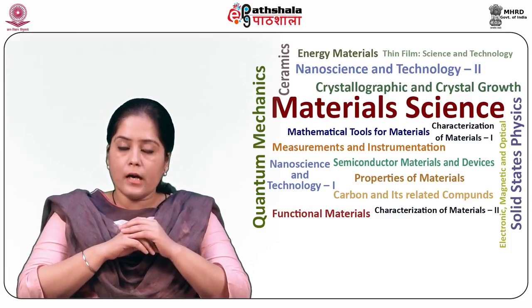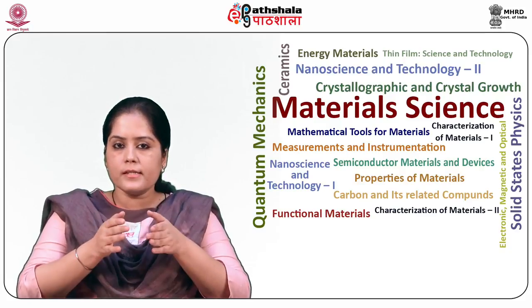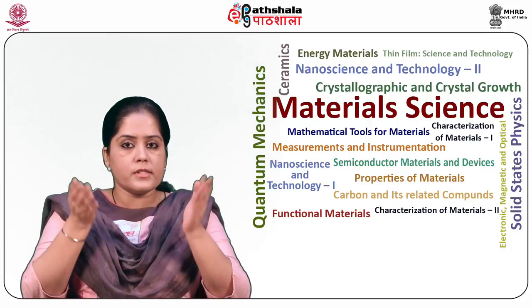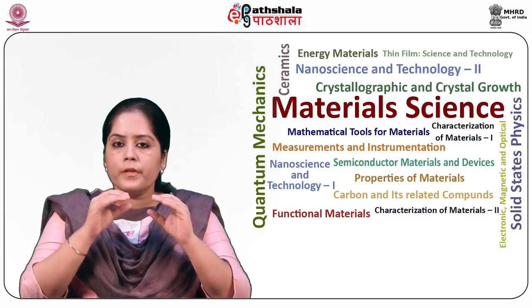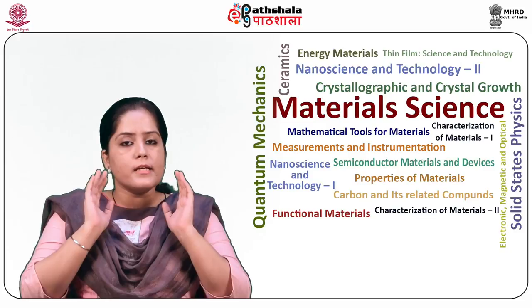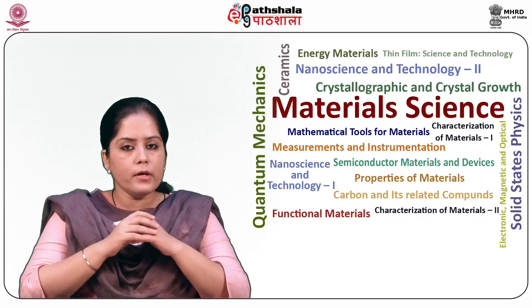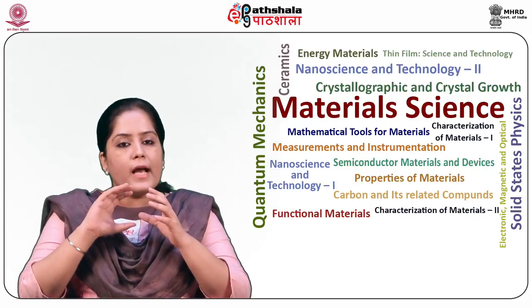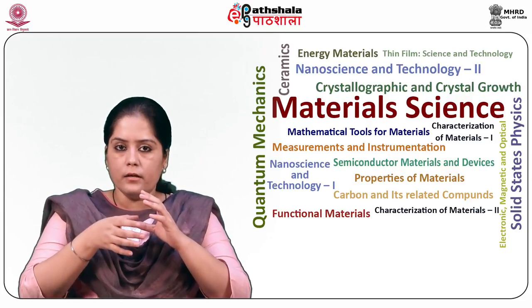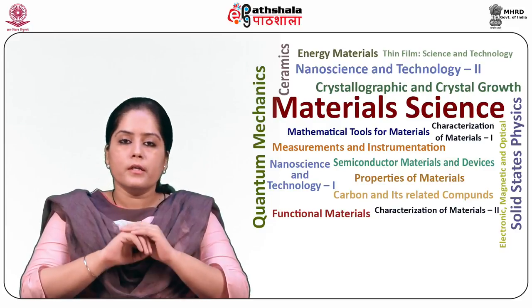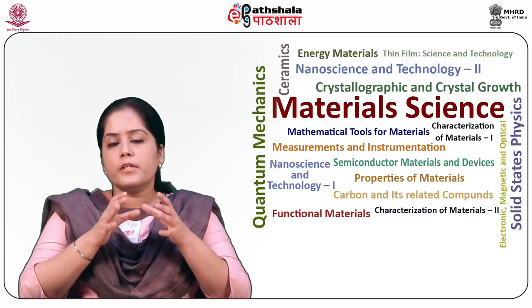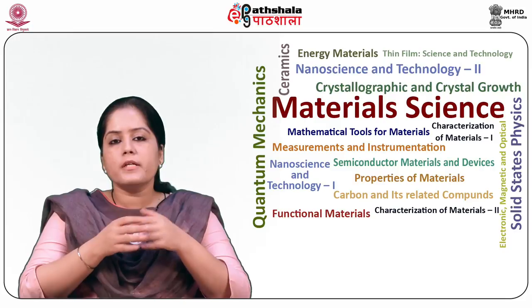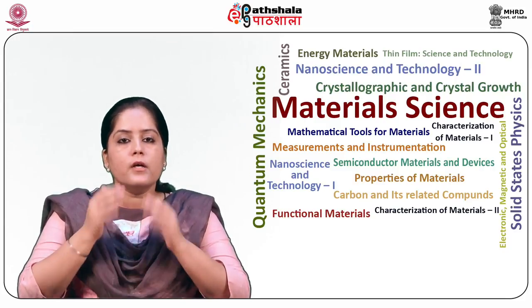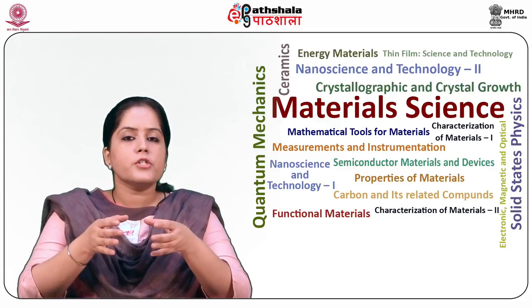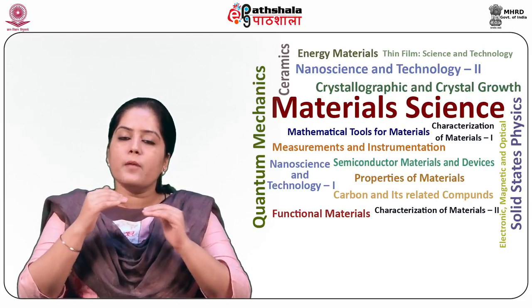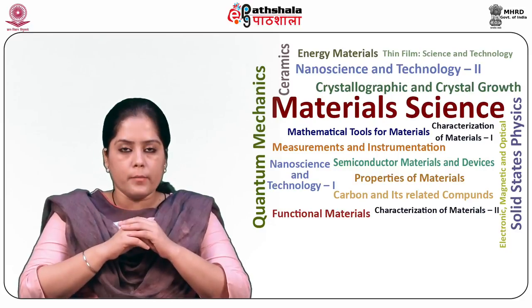The disadvantages of PLD are chances of non-uniform thickness and varied composition across the deposited film, as here the plasma plume formed during the laser ablation process is extremely forward directed. However, this problem can be tackled by rastering of the laser spot across the target material or by substrate rotation during the deposition. Also, the area of the deposited material is quite small, approximately 1 centimeter square, compared to that required for several industrial applications. Deposition of novel materials requires periodic empirical optimization of deposition parameters.